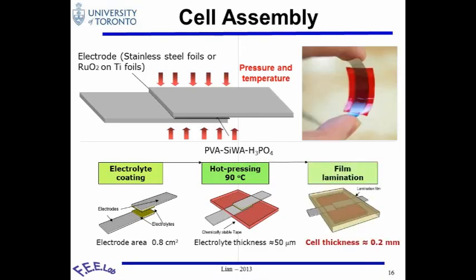So now we have a device. The device itself is like this, and the thickness of the electrolyte is about 50 microns, so it's very, very thin. That's why the conductivity can be very good, and the cell resistance is very low.